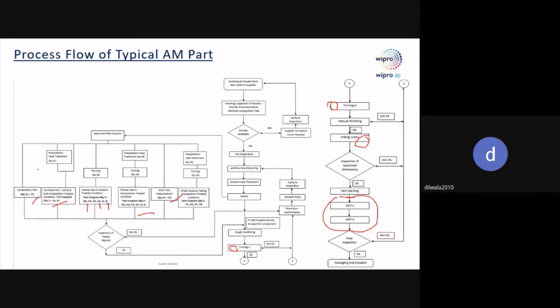So in this, chemical composition was tested at powder level as well as specimen level. Then tensile tests were performed on the coupons in as-built condition as well as after solution treatment and aging condition. Then a stress rupture test was also performed on this part, which was a special requirement from the customer. Then we performed microstructure analysis, chemical composition, and also NDT tests on these parts. We did radiography and fluorescent penetrant inspection.